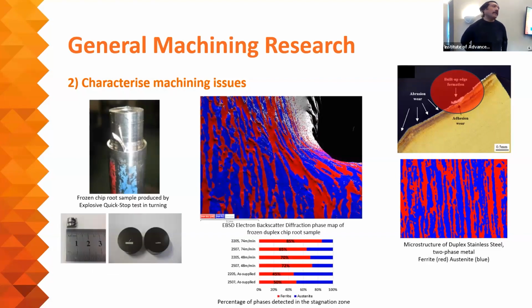You're absolutely right about the scanning electron microscope, it is only able to observe what's happening on the surface. The main issue is, the data which I'm dealing with is only one slice of that chip. And if we look at that chip thickness, it's not very thick as well. So the more you slice it, I mean, I've tried this as well, where I polish a bit of the sample and then observe it under the microscope and then polish it again to try and observe that subsurface. I haven't tried AFM though.